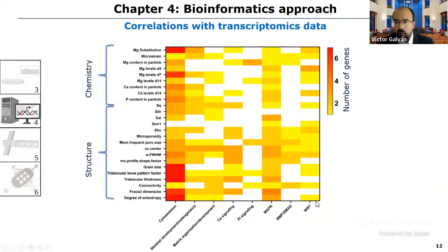Once we had that, we used this to correlate to transcriptomic data. And we found a very high number of correlations, most of which are already described in the literature. For example, looking at the structural parameters, many of them have a high number of correlations with the cytoskeleton, which is something logical, as I explained before. For example, the surface roughness affects the morphology of the cells seeded on the material.